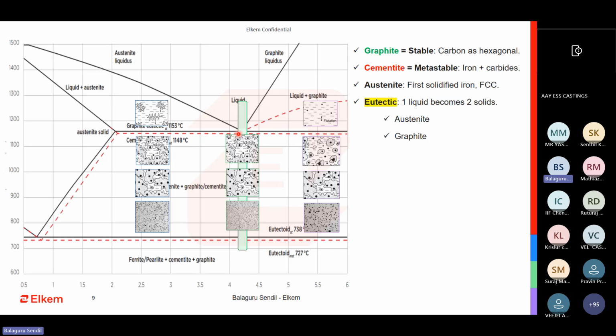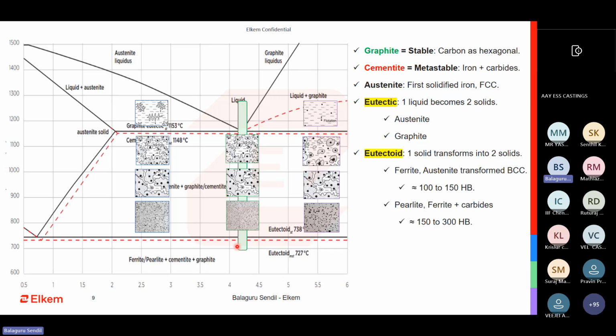The eutectic happens at about 1145, 1146 degrees Celsius. And then you have something called eutectoid, where the austenite that you formed earlier will again break into two different components. It could be either ferrite or pearlite. Ferrite is nothing but the austenite transformed, from one structure to another structure. I have put a picture here, this is a fully ferritic and this is a pearlitic grade. It has a different hardness. Austenite, when transformed to ferrite, is slightly soft. When you have more pearlite, it is more hard. And this actually determines the grades and applications of the cast iron.